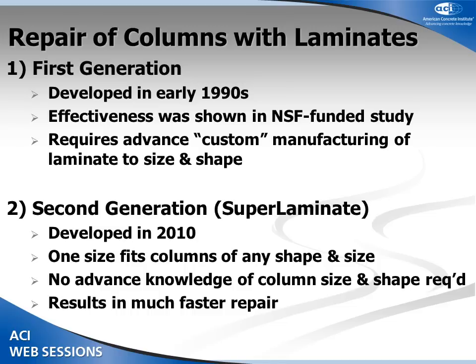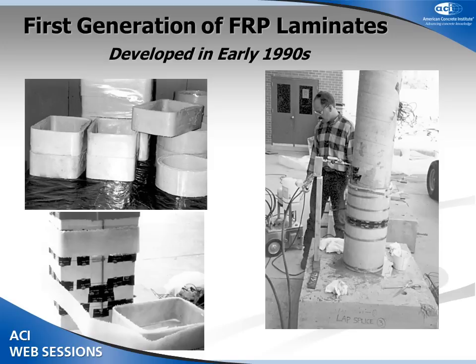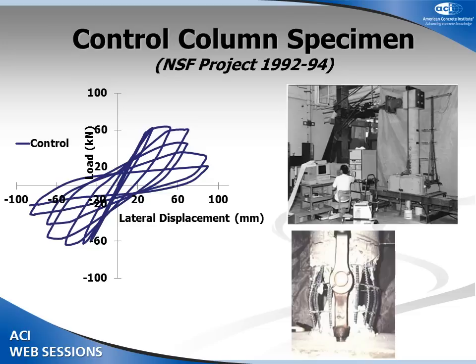The 2010 version of his material is more convenient, easier to apply, and more structurally sound. However, he has not had much time to do the type of research he would like to do, so he's relying on his earlier-generation laminates for research, but says the new material has to be at least as good as what he observed in the lab. The earlier generation, as you can see on the left-hand side, consisted of pre-shaped laminates with enough flexibility to put around a column. He did a lot of testing under an NSF project. On the left-hand side you see the load-displacement relationship of a control column, which was damaged due to lack of confinement in the core, causing longitudinal bars to bulge out and buckle.